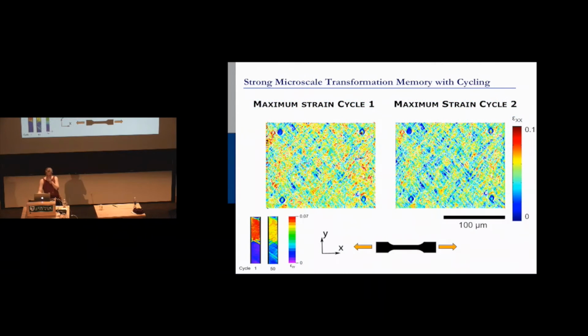Okay, so back to that similarity. You guys remember when we were pulling a specimen and we were seeing the same type of martensite microstructure form over and over again, right? But now let's look at it at the grain level. So this is the maximum strain in this tiny little field of view, 200 microns. In cycle 1, I'm going to flip through cycles 2, 3, and 4, and 5 maybe. And what you're going to see is it's almost like I took the image and just shifted it around a little bit.